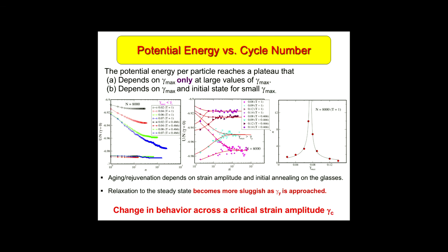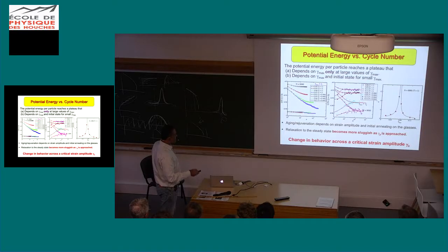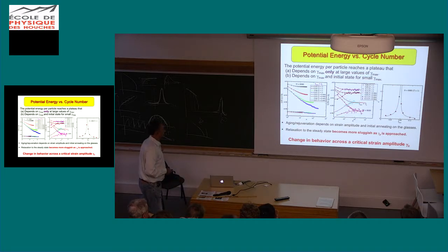Okay, so here is a quick summary of what happens. What I'll be showing a lot is data where there's a maximum amplitude, like I said, that varies between 2% up to 14% in this slide, but it could be a little bit larger. In each case, we look at the properties of the system as a function of the number of cycles, looking at stroboscopic configurations. What you see is at very small amplitudes, the energies decrease. This is starting with a poorly annealed glass, and then they saturate to some value. Likewise, when we start with a well annealed glass, the energies change a little bit, not very significant.